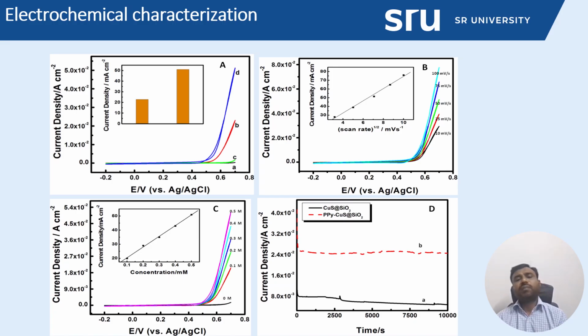It is due to the copper sulfide directly interacting with methanol and electrolyte. Hence, the byproduct may affect the copper sulfide modified surface, so performance slowly decreases. Whereas the polypyrrole coated one has nearly similar stability. The loss is very small compared to copper sulfide alone. So the polypyrrole coated electrode delivered high stability compared to the copper sulfide alone modified glassy carbon electrode.